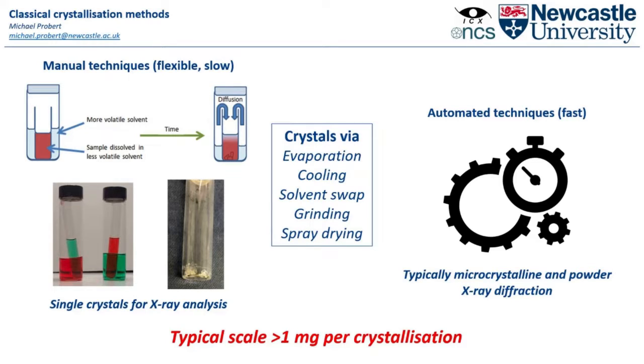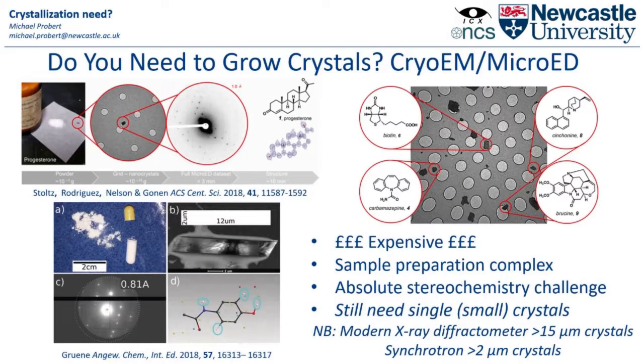So really then, that kind of sets us up nicely, although there's been a kind of game-changing advent of technology in the recent years. So do we need to grow crystals at all? The cryo-EM and micro-ED community have blossomed in this realm, where instead of using X-rays as the incident radiation, we're using an electron beam. And this allows the size of the sample being analysed to be much smaller. And that's because the interaction of our electron beam is much stronger with our sample than the interaction of our X-ray beam.